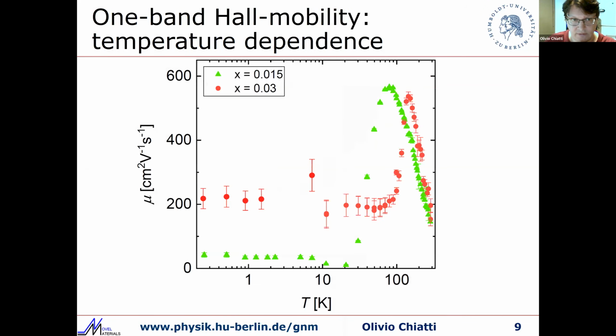Having the resistivity and the charge carrier density, we can also calculate the one-band Hall mobility, and we can see that at high temperatures, the temperature dependence looks a lot like a semiconductor, but it reaches a constant value at lower temperature, which is also something we expect from topological surface states. However, again, we have a surprise here: the mobility of the sample with lower vanadium concentration is definitely lower than the other sample.